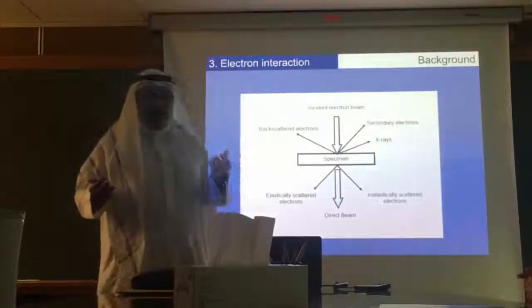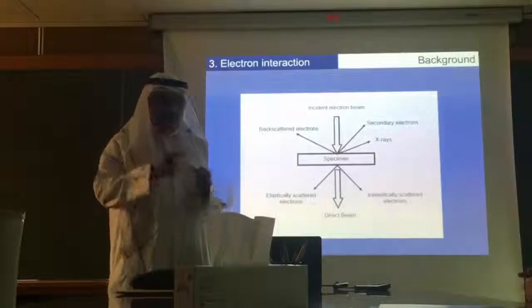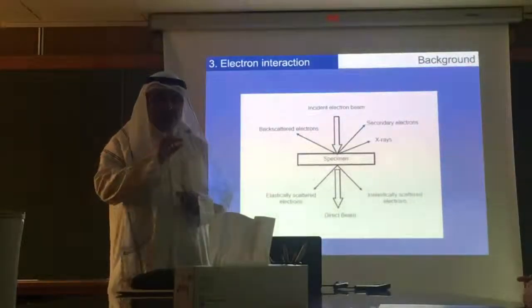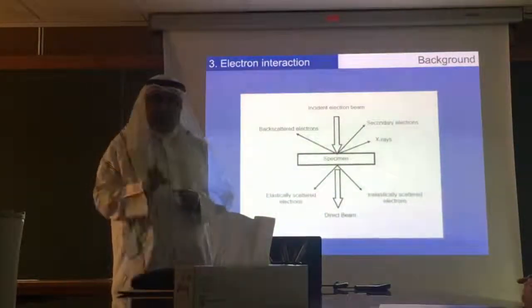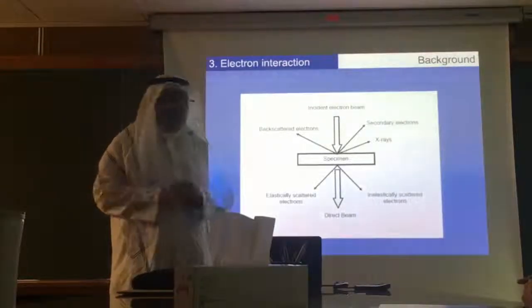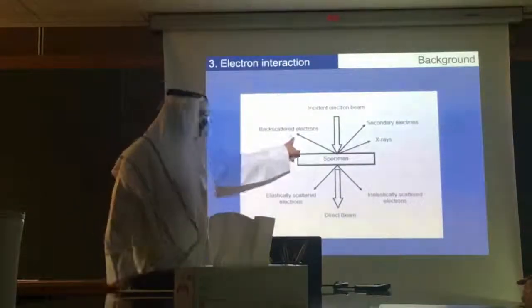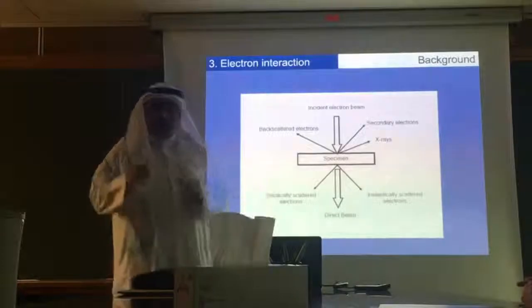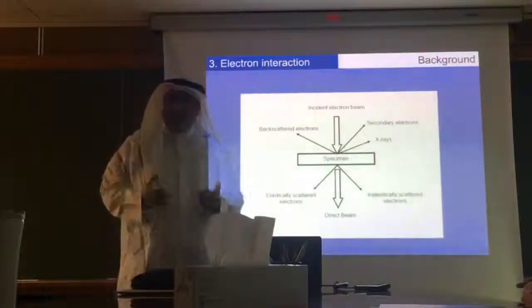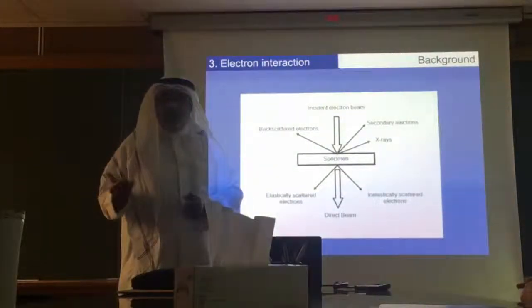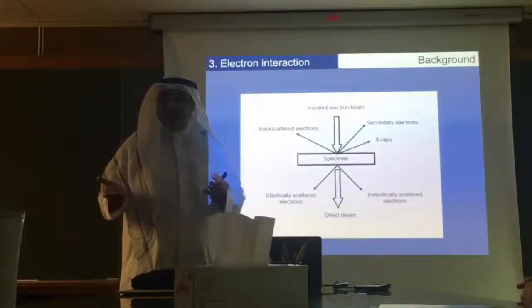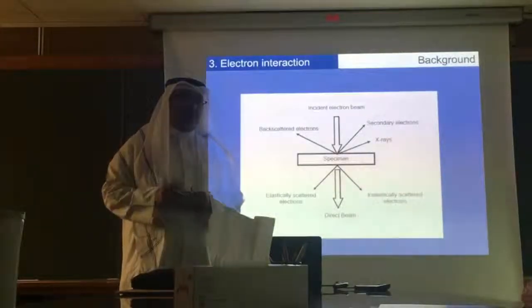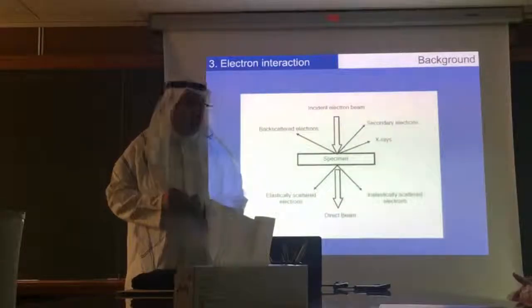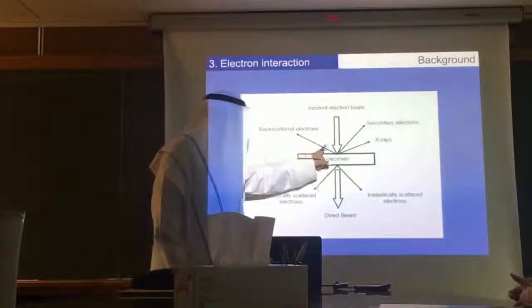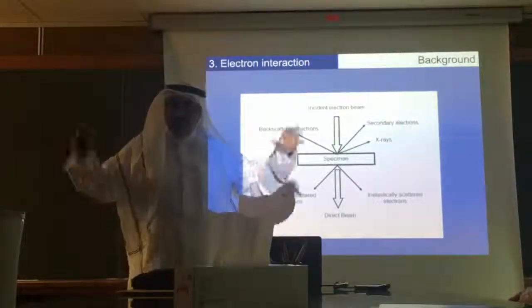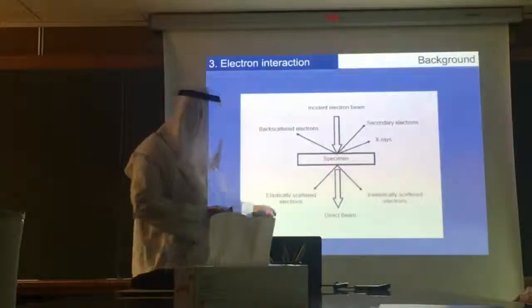If you have a material and you want to know the thickness, for example, if you have a metal and you want to know the thickness of the gold plating, because underneath the gold plating is a cover, for example. This is the best technique to do it, because the gold is a heavy metal, while the cover is a lighter metal. The heavy metal in the microscopy will look brighter, and the light metal will look darker because there is less electron coming from inside. So this is good for contrast, while this one is good for the shape and for the morphology of the particles.